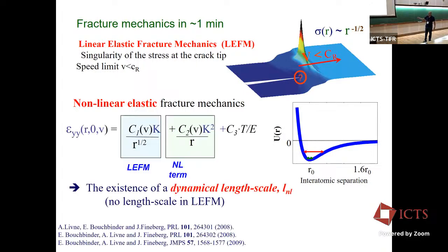Just to remind you about fracture mechanics. We looked at this. We derived this nonlinear scale as the crossover scale between the solution for linear elastic fracture mechanics and the nonlinear term, which has a 1 over r singularity. The crossover is this scale here, which will be the star of our show.